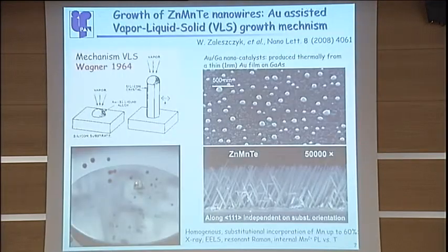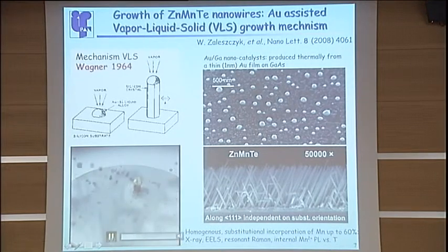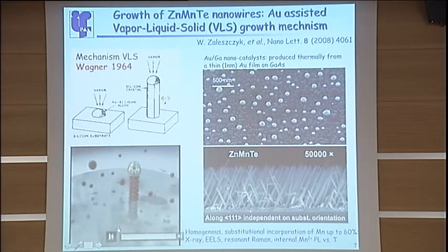You just have to produce somehow a eutectic ball, which is liquid during the growth. And then you supply a flux of materials from which you want to grow your nanowires. In our case, it is zinc manganese telluride. And then as soon as this nanoball is saturated with materials you want to supply, it will keep growing, producing this nanowire.